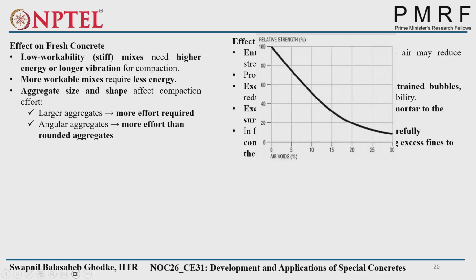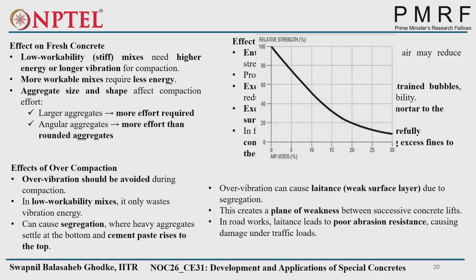In this plot you can see for 10% of air voids, you are almost reducing your strength by 50%. So that much effect the void has on the strength. Similarly, with more voids, the durability will also be low. So voids have a very wide effect on the concrete properties.